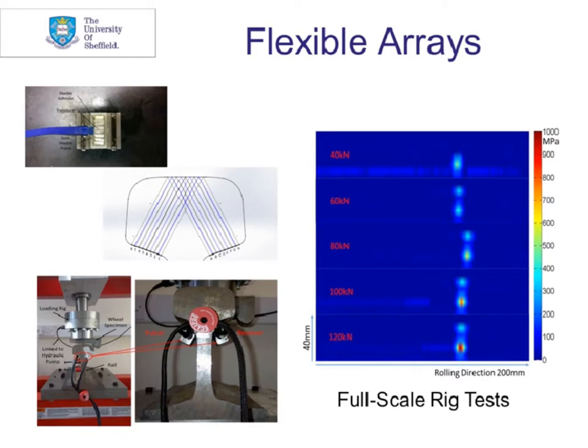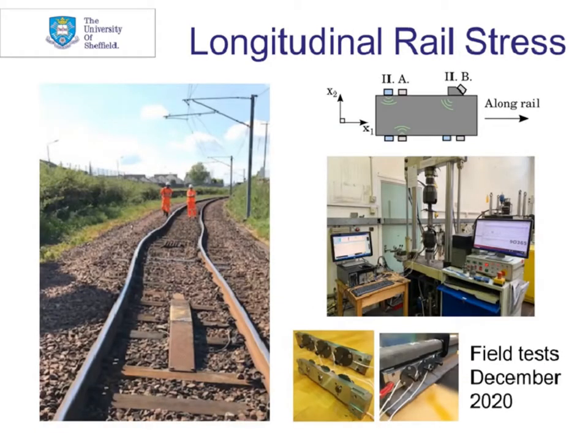In the meantime, we've started to apply the ultrasonic technique to a slightly different track-related problem. Longitudinal stress in the rails causes problems. You can see here an example of where some problems have arisen during the summer when the track gets hot and has buckled. So this is why you quite often get speed restrictions in hot weather to try and avoid this happening. So we've developed a technique by which we can actually monitor the stress in the rail.